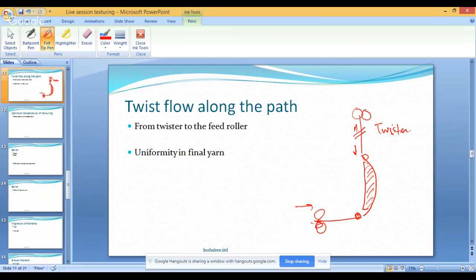So the question comes, that means the yarn is going to be non-uniformly twisted? Not necessarily, because the same yarn which at the point of the feed roller has less twist, as it is moving up, the twist obviously is increasing again. So every part of the yarn will go through the same process, initially less twist, then more twist, and then more twist in the heater, and after that getting cooled. So when it gets cooled, then you have to untwist. So this is an important part, that you must be able to cool the yarn before untwisting takes place. If a hot yarn is untwisted, all the setting that we are interested in would not be seen.